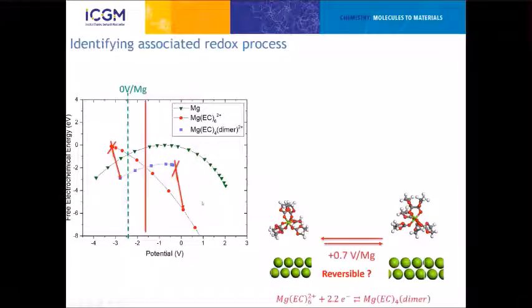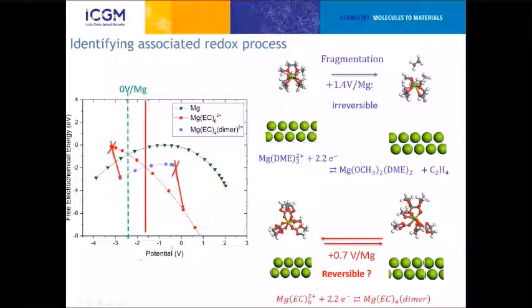We get, of course, the potential, the thermodynamic process. We get that the reduction occurs at plus 0.7 versus magnesium, meaning that the ethylene carbonate is reduced before the magnesium. That can be a problem. This also occurs for the DME molecule, but this time with fragmentation. And of course, the fragmentation is irreversible. When the fragmentation occurs, there's no turning back because the ethylene molecule cannot find its way back to reform the initial DME. This also is associated not with the reduction of the magnesium, but with a reduction of the DME molecules.